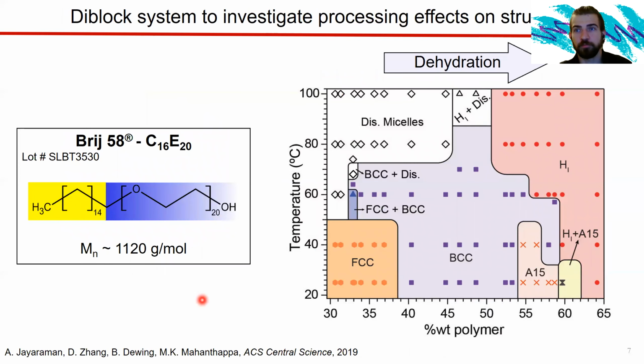So the specific system that I'll be talking about today is Brij 58 in water. Brij 58 is a simple surfactant molecule where you have an alkane tail that's about 16 carbons long, and you have a polyethylene oxide tail that's 20 units long. So you get this phase behavior on the right. We have temperature and weight percent of the polymer. Now, you'll see some of those phases I just talked about: face center cubic, body center cubic, hexagonally packed cylinders, and also Frank-Kasper A15, in addition to a disordered phase that you see over here, where there's no more crystalline structure. It's more like a liquid micellar state.